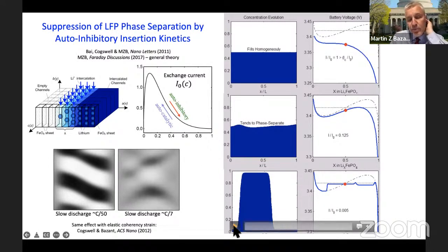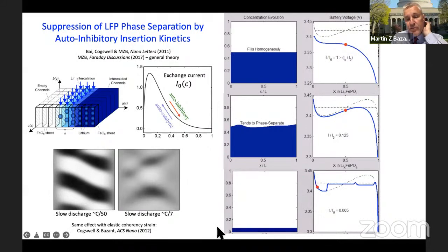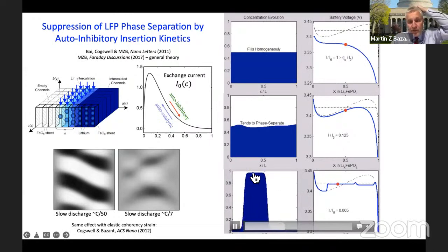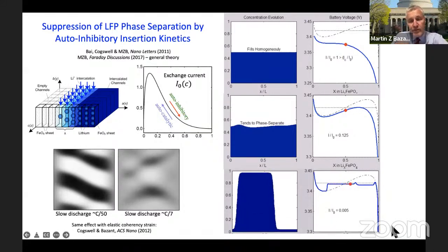And so here's a simple model of insertion of lithium into this crystal. It starts at uniform, but when you get to the so-called spinodal point, where you have a linear instability to phase separation, notice we now picked up the high density phase and the low density phase, which correspond to the endpoints of the voltage plateau. And on the right, you can see the voltage is simply following the plateau as one phase is being converted into the other phase. So this is at a low rate.